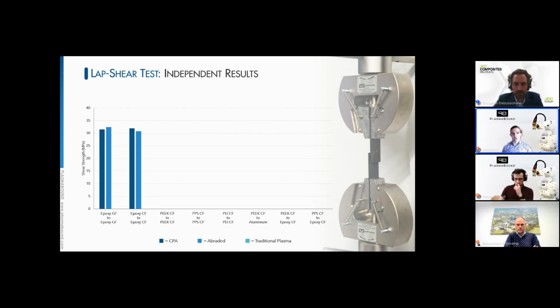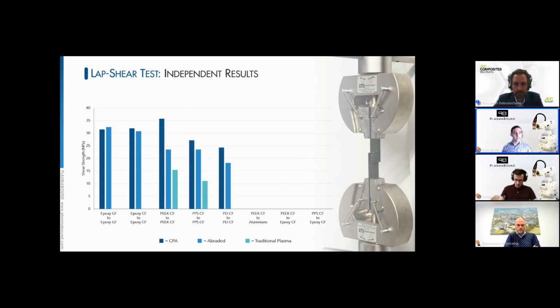When we moved into similar thermoplastic systems, this was again demonstrated. The PEEK to PEEK, PPS to PPS, and PEI to PEI CF systems, we caused substrate failure in all three of these systems compared to abrasion and traditional plasma, which didn't perform as high for these particular material types and joints.